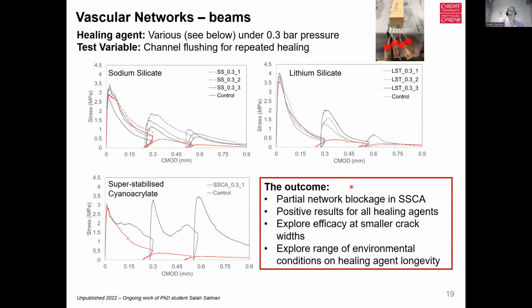For our vascular network beams, when we look at different healing agents, we have sodium silicate, lithium silicate, and our super stabilized cyanoacrylate. So that's really a super glue that we've tweaked ever so slightly to make it more stable at its point of encapsulation and not quite as reactive. We saw that we could achieve repeated cycles of healing over 2 to 3 cycles. And what we have with our cyanoacrylate is an increased peak strength in each one, which is very encouraging in terms of demonstrating that we could completely recover any damage that we saw in the first and second load cycles.